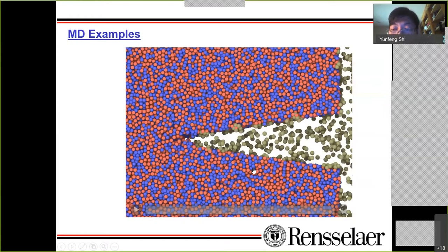So the way to mitigate that is that you can either anneal the shell, so you remove the stress, or, of course, you store it without any chemical environment. So this is quite a complicated phenomenon, right? But very, very important. You can see a lot of failures around the world have a chemical component, not only a stress component to it, right? So this is a really fundamental question: how the chemical concentrations affect the overall crack growth rate at a given mechanical agitation, right? The mechanical agitation is characterized using the stress intensity factor. So, okay, here I will show you this animation.